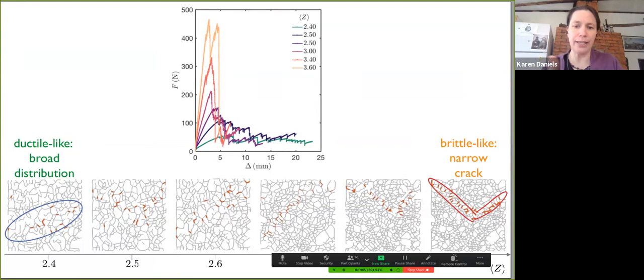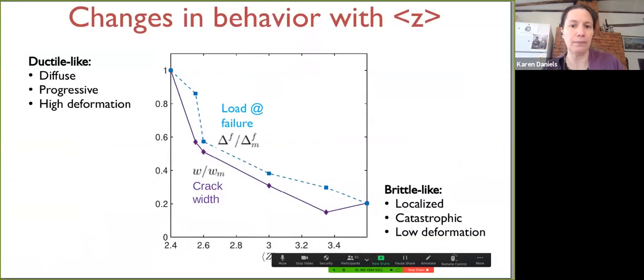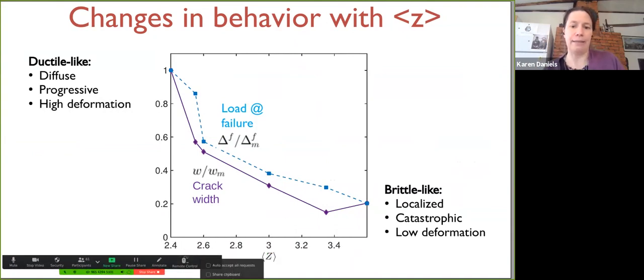In between, you can see from the graph a combination of those 2 behaviors. Sometimes you get a nice crack, sometimes you get distributed failure, and this is being tuned by the degree of connectivity. We characterize that a couple of different ways. One is, as I mentioned, looking at the ratio of how wide the crack is; we have a measure for that, the purple line. We also have a measure for the load at failure. These have been normalized, so don't worry about how I've normalized them. They both follow the same trend, and so we can use this to classify things as being either brittle-like or ductile-like. In fact, there's a whole continuum of behaviors between that.